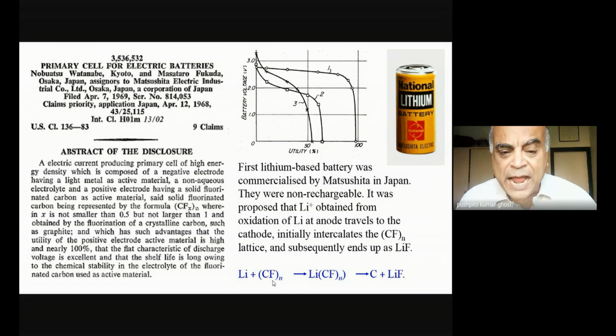Why did they do that? Because the reaction they were aiming for was that at the anode, lithium will become lithium plus, which it did, and at the cathode, the electron actually came here. It initially became negatively charged because that electron came to the cathode, like CFn minus. This lithium, which became lithium ion, will obviously tend to go towards the cathode, and it will form this kind of a compound. But the interesting thing is that once the electron gets pumped into this fluorinated graphite, the fluoride comes out.